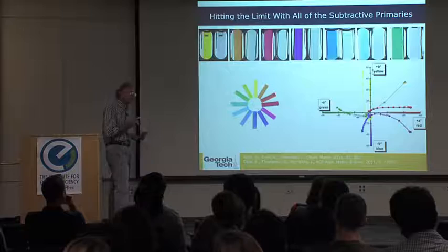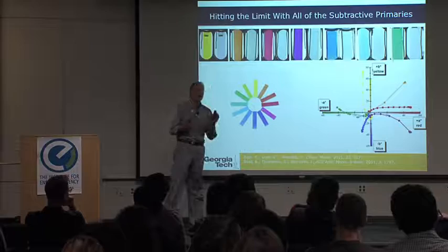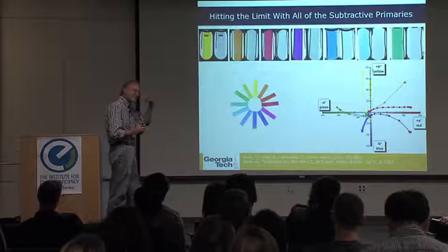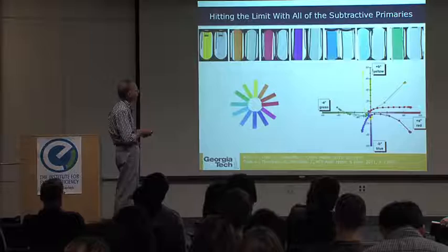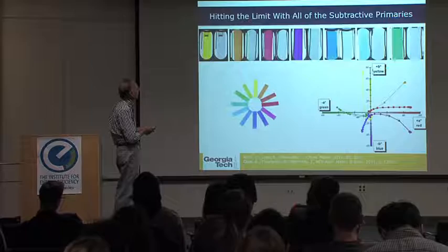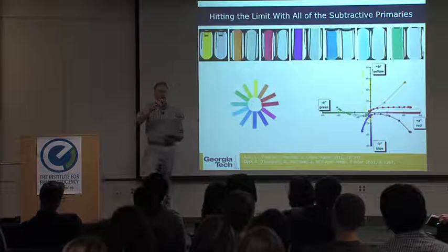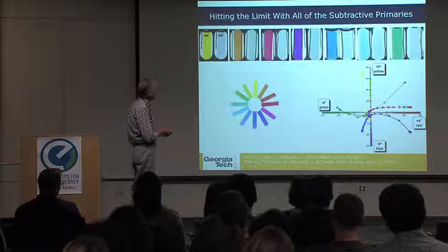And so with that, in these soluble polymers, our yellow polymer can go transmissive, our orange polymer transmissive, red, purple, all these go transmissive. Now we use this a-star, b-star color plot as a way of keeping up with what's happening in the colors. And so let me talk you through this, because we'll use these. The idea being that your eye is a nonlinear detector, and the sensitivity to color is a function of the wavelength of light. And so what we can do is take a spectrum and break it down to how your eye will respond and apply color coordinates of red to green. So positive a, red, negative a, green, positive b, yellow, negative b, blue, and then determine where any material sits in those color coordinates. And then as we change the electrochemical potential to that film, for example, for this red material, we can track the color track as that material goes from being very vibrant red ultimately to a color neutral, and in this case, a transmissive film.